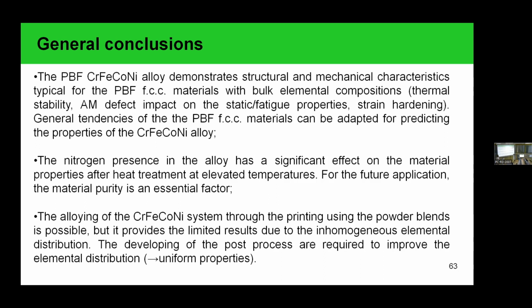Also, we observed that nitrogen, even in the smallest content, affects the structural and even mechanical properties after heat treatment at elevated annealing temperatures. So the purity of the material is a key factor for application at elevated temperatures. And talking about the alloying of our four-component system through printing using powder blends, generally we can conclude that it's possible, and it's possible to improve the inhomogeneity by applying high temperature annealing,